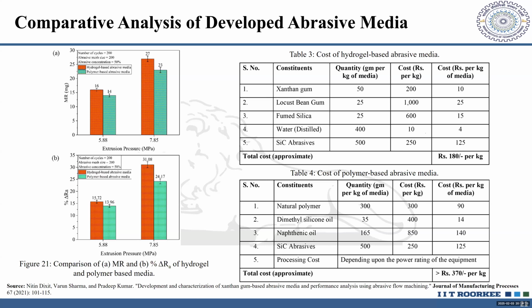It is also cost wise that these hydrogel based media are good enough. For example, if I compare making 1 kg of that particular media, our approach is going to cost just 180 rupees per kg, whereas the conventional polymer based abrasive media, which even some of the research labs are using, costs around 370 rupees a kg. So from the economics point of view also, this particular process could be used.